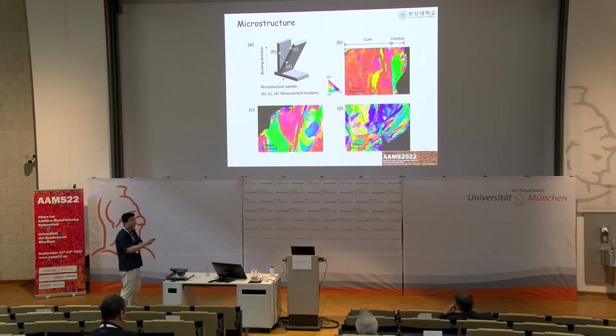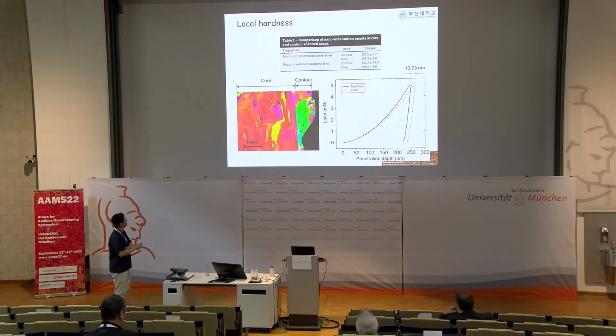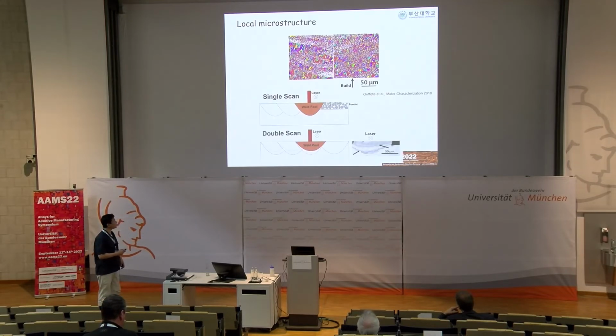Downskin, we have really fine microstructure, and in the vertical sample, if we measure the local hardness by nanoindentation, we found that the nano hardness near where the laser contour scanning is put is pronouncedly higher than in the core. And actually,